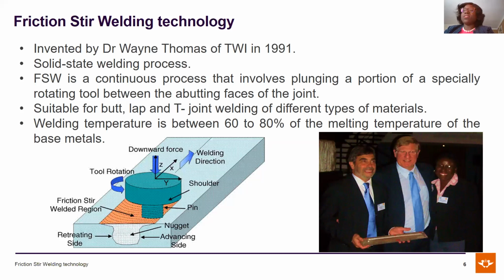Over the years, the technology has had a lot of improvement. It is suitable for butt, lap, T-joint, and so many other joint configurations. And the welding temperature is usually between 60 to 80% of the melting temperature of the base materials. I recall when I performed welds using the friction stir welding technology, I had the opportunity to insert thermocouples in the welding interface, and temperatures recorded were between 60 and 70% of the melting temperature.